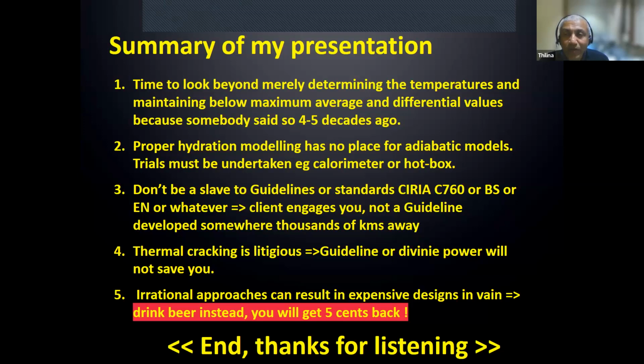So what would you like to have? Through-depth cracks or surface cracking? In a water retaining structure, through-depth cracking is the end of the structure. As I said in the desal, cracks with through-depth, because they left it to the contractor to do the design.